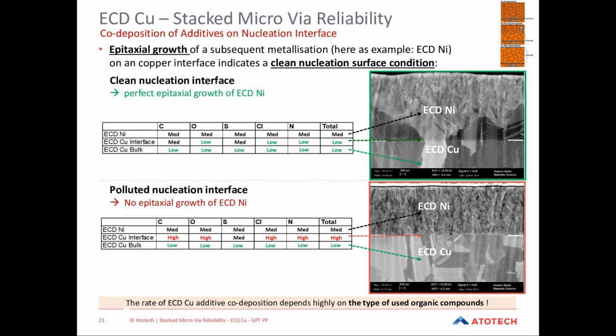Here I have an example for you about two different scenarios you can run into. The first scenario is visible on top. You see here a build-up of electrolytic copper and a build-up of electrolytic nickel on top. And in between, you see that the crystallization from electrolytic copper, this crystal growing in shape and in size, will be continued in the electrolytic nickel application. So what you can see on this green highlighted image is a so-called epitaxial growth of electrolytic nickel on electrolytic copper.